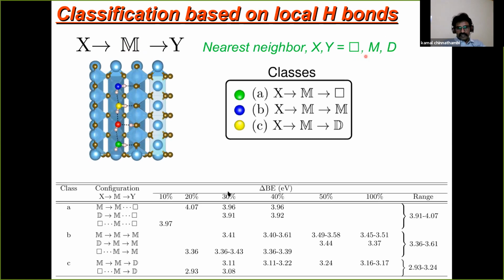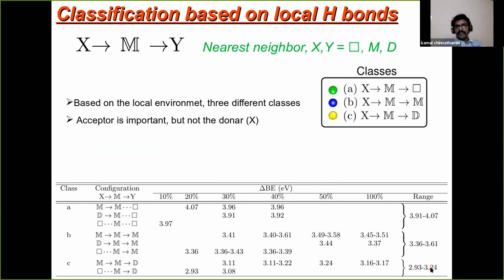The most important thing is this table, which we got for all the different possibilities. Then we can see that the binding energy differences between the water molecules and the titanium oxide group into 3 different classes. It strongly depends on the Y, which is the acceptor. It hardly depends on the X, so it is not playing any role here at all. So using this, we can clearly see that there are different classes. The most important thing is that whenever you have a dissociated molecule as an acceptor, you have a very low binding energy.